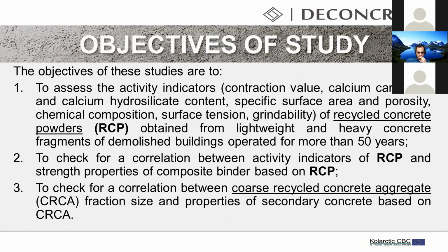The first objective of the study is to assess the activity indicators of recycled concrete powders obtained from lightweight and heavy concrete fragments of a demolished building operated for more than 50 years. We used several indicators: contraction value, calcium carbonate and calcium hydrosilicate content, specific surface area and porosity, chemical composition, surface tension, and grindability. The second is to check for correlation between activity indicators of recycled concrete powders and strength properties of composite binders based on them, and to check for correlation between coarse recycled concrete aggregate fraction size and properties of secondary concrete based on them.